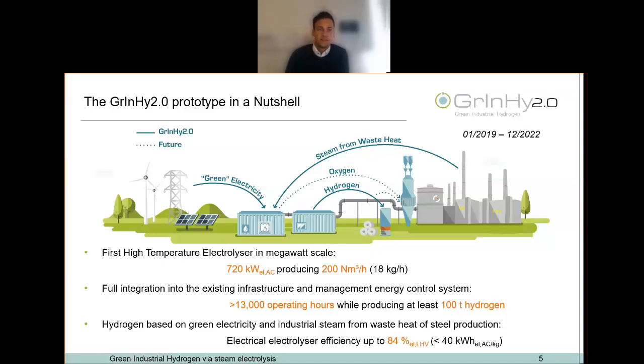By using steam from inevitable waste heat sources of the steel making processes, we want to reach electrolyzer efficiencies of up to 84% based on the lower heating value, which is quite remarkable because it means that it's equivalent to less than 40 kilowatt hours per kilogram of hydrogen. Next slide, please.